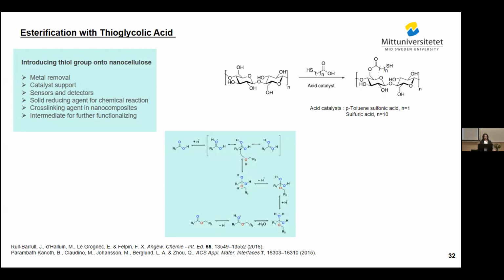Here are the groups that worked with direct esterification of thioglycolic acid on filter paper or on CNC, but they used acids, paratoluenesulfonic acid and sulfuric acid, and the one with sulfuric acid was for 3 days. The reaction was for 3 days. Then there is a possibility of hydrolyzing CNC or nanocellulose with this acid. Then we wanted to try with our mild condition to see how it would work.